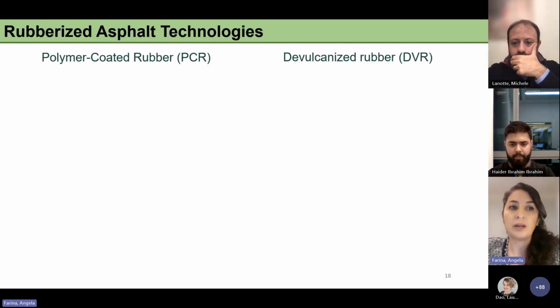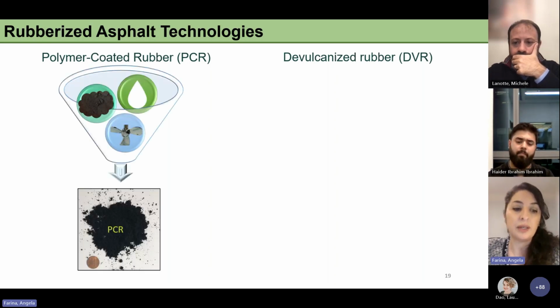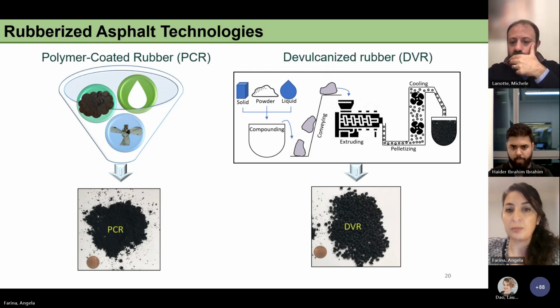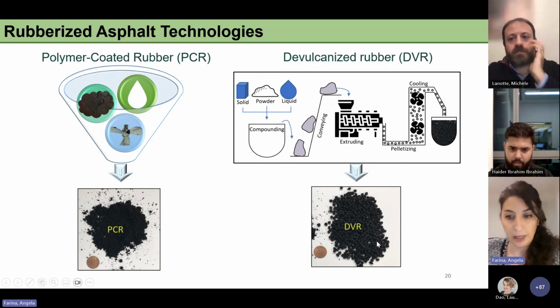And in particular, I focus on the use of two crumb rubber technologies, the polymer coated rubber and the devulcanized rubber. The polymer coated rubber is a rubber with the surface of the particles covered by a polymer emulsion that can be SBS or SBR. Instead, the devulcanized rubber is obtained by a chemical and mechanical process. The chemical process is necessary for the devulcanization of the rubber, and the mechanical process to create the pellets.